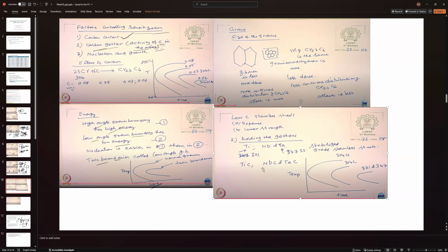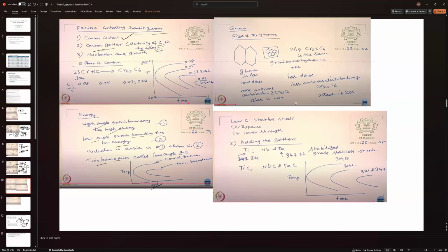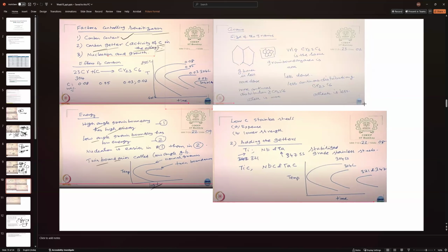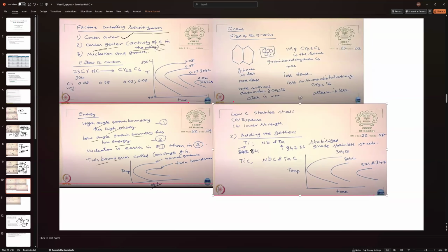So your chromium provides your passivity. If the carbon was free to react with the chromium, it would form chromium carbide and consume the chromium from the region around the precipitate, and you lose your passivity. To counteract that, we are adding titanium, these stabilizing elements. These consume the carbon, so your chromium is not consumed and you maintain your passivity. So to maintain the passivity, we are removing the carbon by adding other carbide forming elements. Chromium carbide is not forming; instead, these other carbides are forming. Okay, correct.